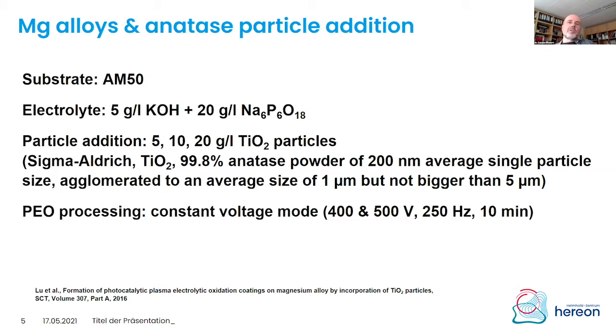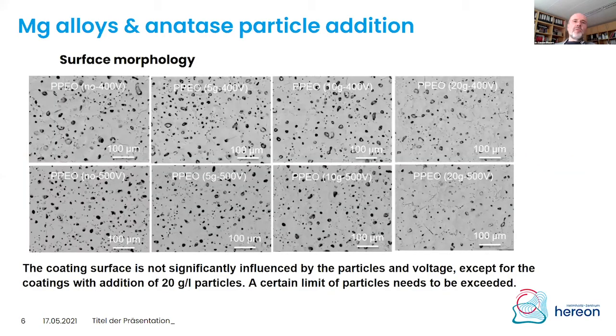So it was a constant voltage processing in the PEO case at 400 and 500 volts, basically to see the effect of different energy levels on the incorporation of the particles. So when we look first at the surface morphology, in the upper row you see the 400 volts treatment, and in the lower row we have the 500 volts treatment.